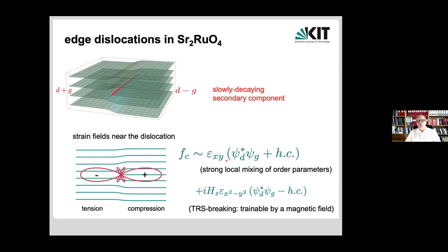Among others, for example, if you look at D and G in the B2G symmetry channel, you have a bilinear coupling between these two order parameters, and therefore you would naturally mix in G. In addition, when you go to the left or to the right of a dislocation, you would either have tension or compression. So the sign of the coupling changes if you go from the left to the right. And that directly gives you D plus G if you're far away on the one side and D minus G if you're far away on the other side.